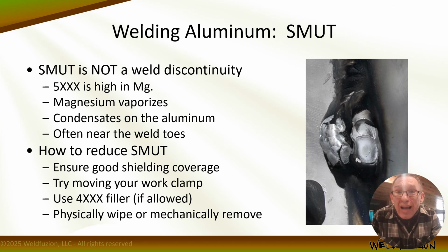This is most commonly seen with gas metal arc welding with 5000 series filler metals, and it's not very common in TIG welding, and most often is only observed if something goes wrong, like when you dip your tungsten in the weld pool, right? Make sure you have good shielding gas coverage, and you can also try moving your work clamp if you notice it collecting in one area and not another, because the magnetic field will have an impact on where the material wants to condense and the direction that it will follow, right? So the magnetic field, the welding current, has an effect.